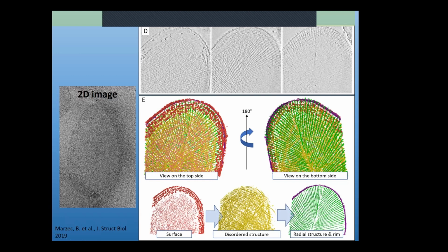What is really interesting is that around the rim, we found a globular structure that is absent from the middle. So it's not just chemically different, it's morphologically different, which again makes sense, because if we have nucleation sites in here, that means you must have proteins or polysaccharides, whatever, that are absent from the middle, so that you get nucleation only in this region.